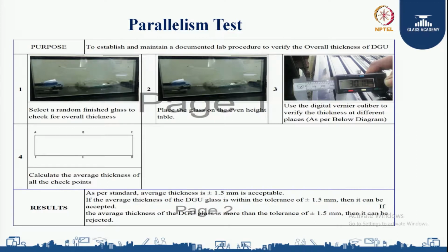As per the standard, the average thickness allowed is plus or minus 1.5 mm. If the average thickness of the DGU glass is within this tolerance, it is accepted. If it exceeds the tolerance, it is rejected.